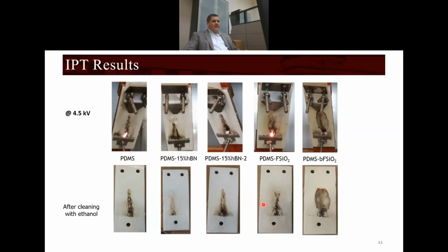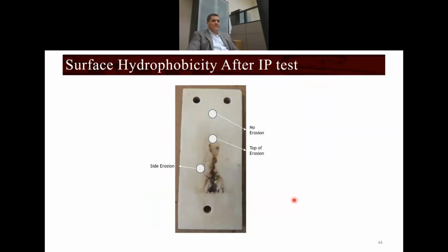This is just to show you the samples after the cleaning, because sometimes you get some char, but that char is mostly because of the conductive electrolyte. As Dr. Ayman mentioned, we add the Triton conductive electrolyte to make the surface conductive. Sometimes what is burning is this conductive electrolyte, not the coating itself. This is why we clean it, to make sure that what is burning is actually the coating, not the conductive electrolyte.